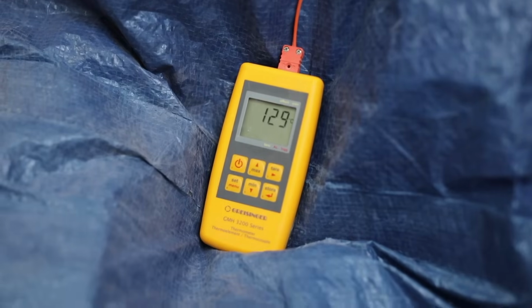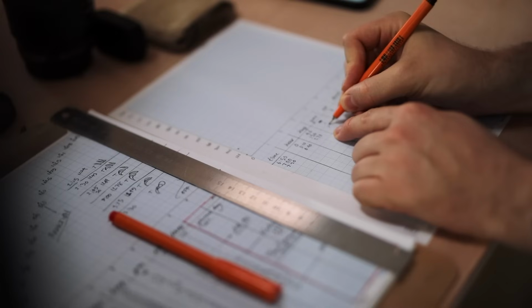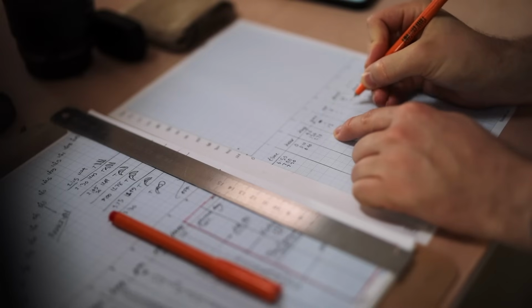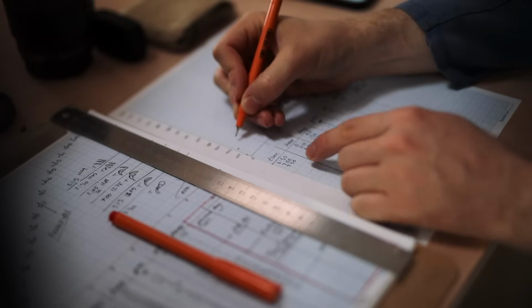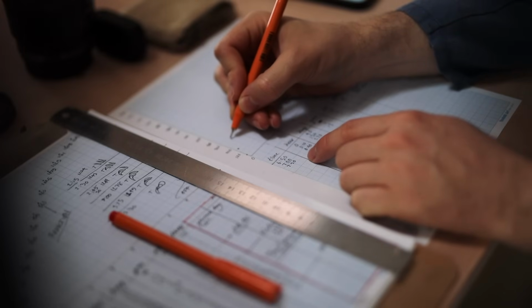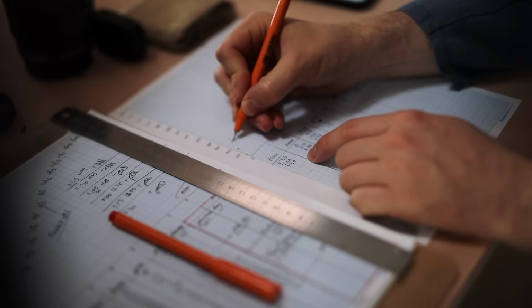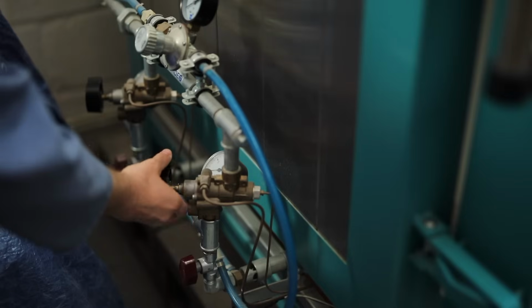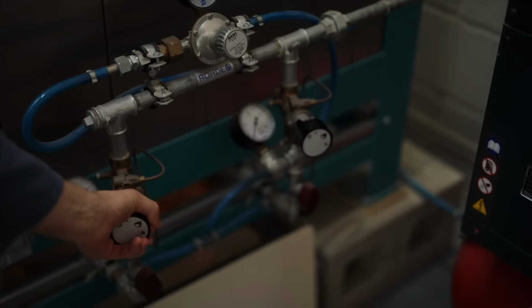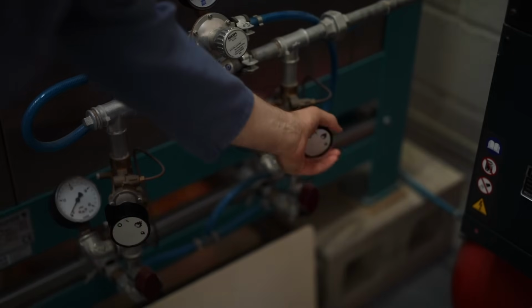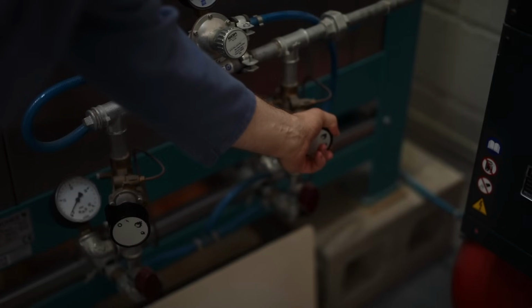I don't raise the temperature too rapidly, as by doing so you can cause the pots themselves to explode, as even though they're dry there is still moisture inside them, and if all of that suddenly turns to steam, then the pots can explode and shatter into hundreds of pieces. Every 30 minutes I log all the necessary data, and I follow previous firing logs to keep me on track, which for this beginning period is very straightforward, as all I'm really doing is just turning up the gas gradually every 30 minutes or so.